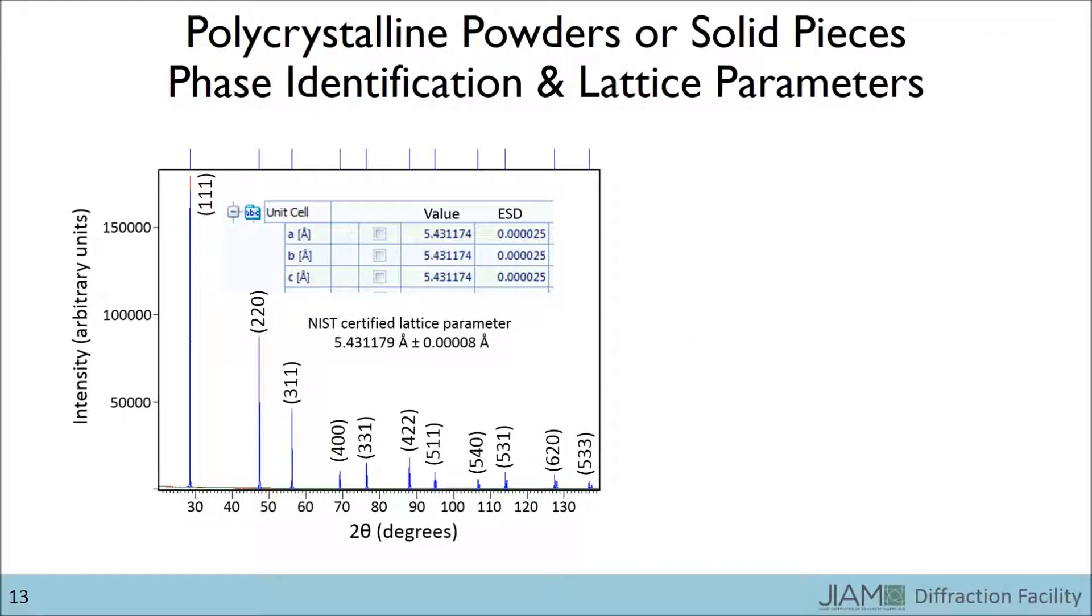A useful aspect of diffraction is that each material has its own diffraction pattern. The example shown here is for silicon, and each peak corresponds to a particular atomic plane as indicated. After collecting a diffraction pattern for your material, you can compare it to the PDF4 Plus database which contains over 380,000 other patterns to find a match. Access to the PDF4 Plus database is available in the diffraction facility.